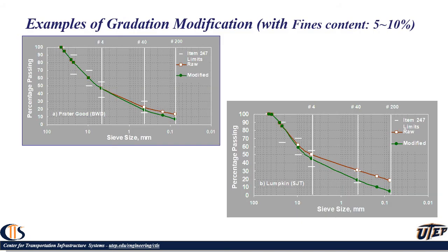As an example of gradation modifications, we started just basically removing fines from the materials because of the relaxed values that we had. We found that the gradation needs to be modified significantly more. The change in the gradation by removing fines was only marginally successful.